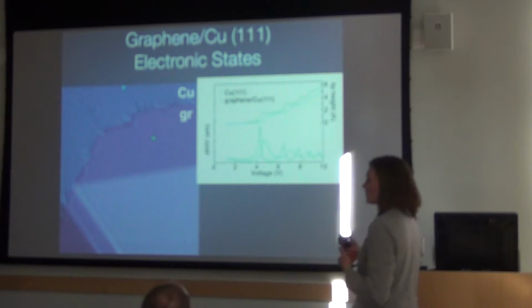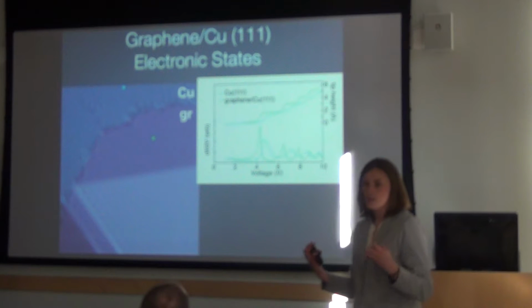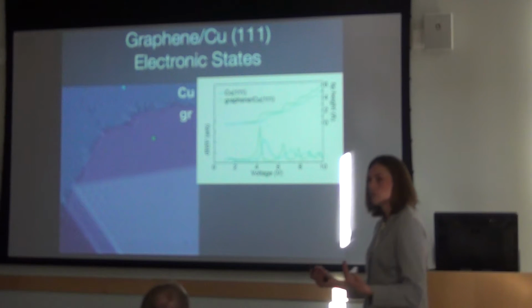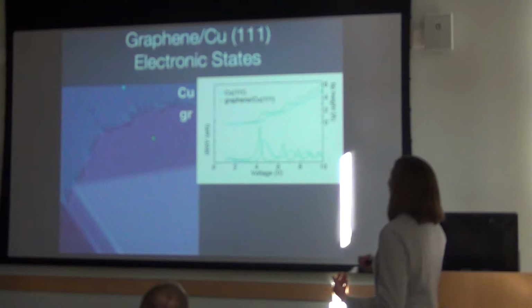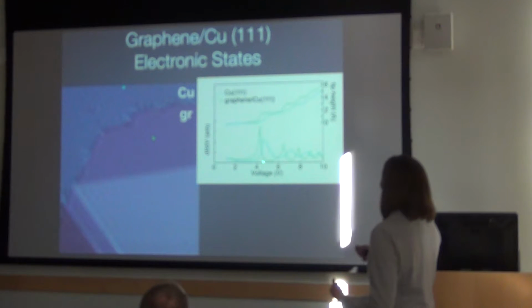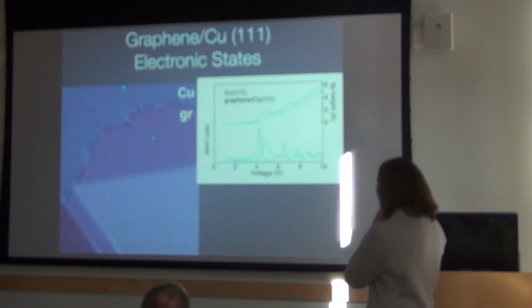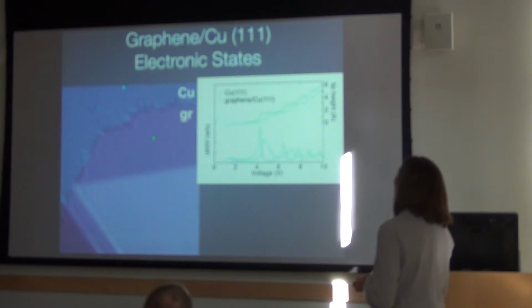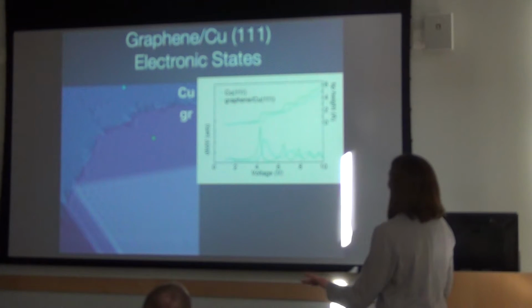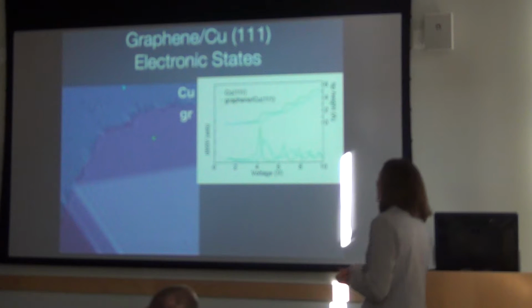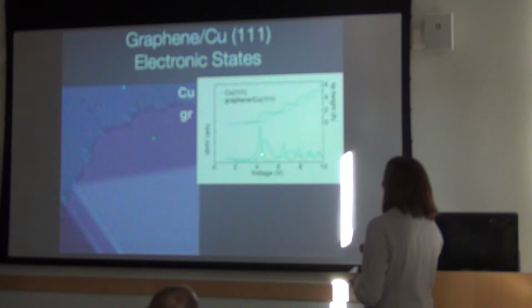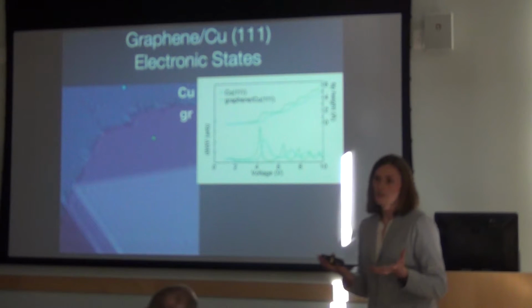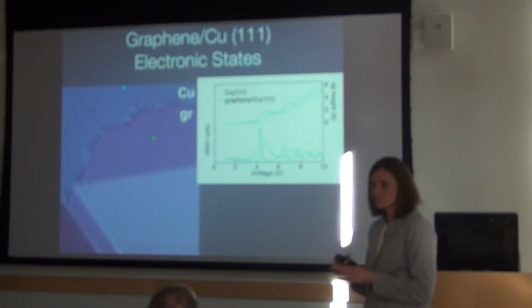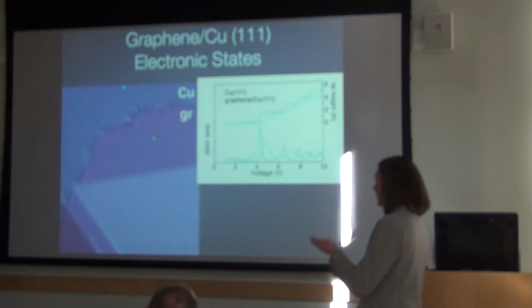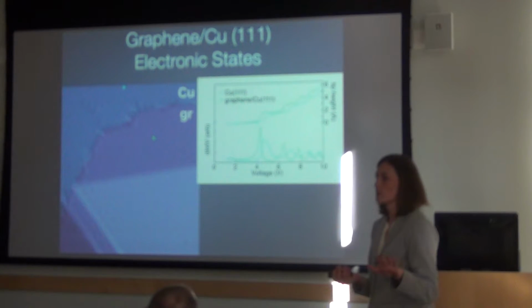Every time it hits one of these image potential states, all of a sudden there are a lot more states for the electrons to tunnel into. So the tip keeps backing up to keep the current constant. And you see these corresponding spikes in dI/dV. And we can also here compare the bare copper to the graphene copper. And we can get a lot of information out of here. One of the obvious things is that these image potential states are shifted. And this reflects a change in the work function between the graphene covered regions and the bare regions.